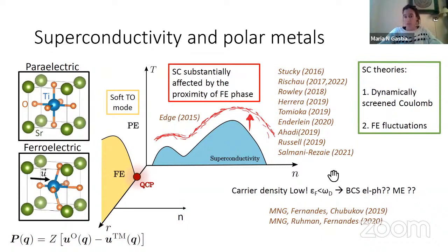And then, that being said, I would also like to point out that this is a problem that has been studied quite a bit. Lately, I would say that the two main pairing mechanisms have been using either the dynamically screened Coulomb interaction due to longitudinal modes. This is, for example, what you would have if you want to explain a system that is superconducting due to plasmons. But the one that I'm going to discuss today is the second one, where you couple the electrons directly via some exchange coupling to the ferroelectric fluctuations.